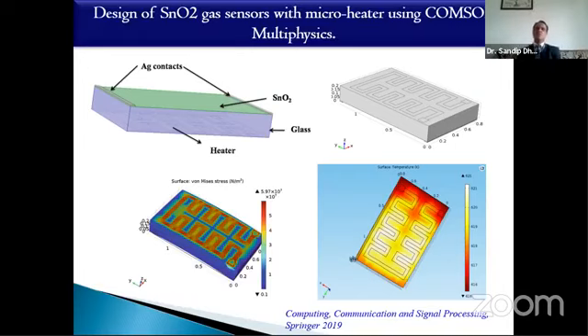Most SnO2 based sensors perform very well at this 350 degrees Celsius, and these results also show that the stress is very low in the sample at this higher temperature. Normally, what happens if we heat these films? Since the film has a rectangular shape, the strain is much higher as compared to a cylindrical shape. So at 350 degrees Celsius, it can withstand, and the glass is also not affected when I apply this voltage to heat the sensor. This article we published in Springer last year.